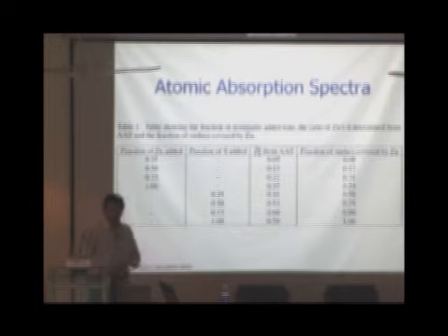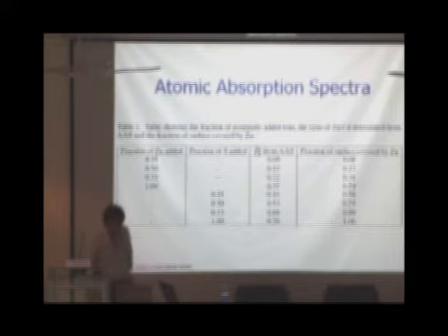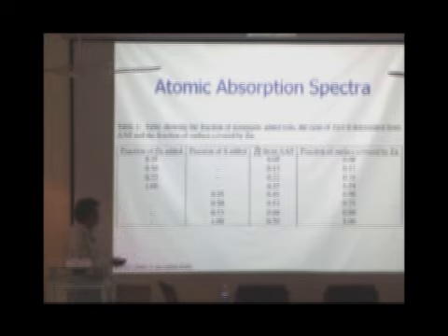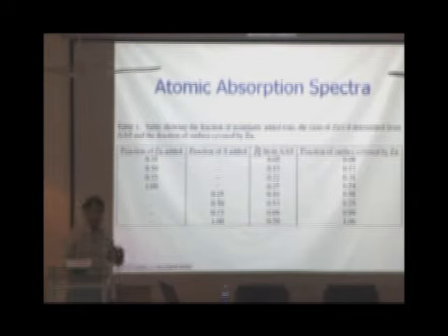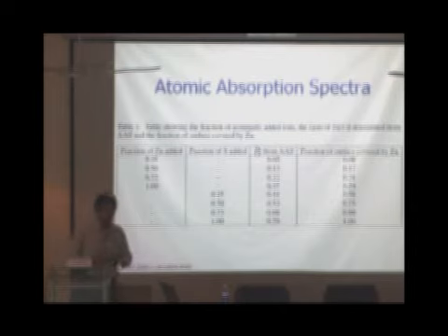And what we realized was, there's a great deal more to these nanocrystals. They all are crystalline in nature, and each crystal has facets or faces. So different faces have different energies. And when we compared these different facets, we realized that some of the most reactive facets belong in this 8% of zinc coverage. So first, zinc comes in and attacks all these very reactive facets. Gain of intensity. Then 17% corresponds to the next reactive set of facets. So the surface of these particles is so important that it plays an immense role in the luminescence properties.